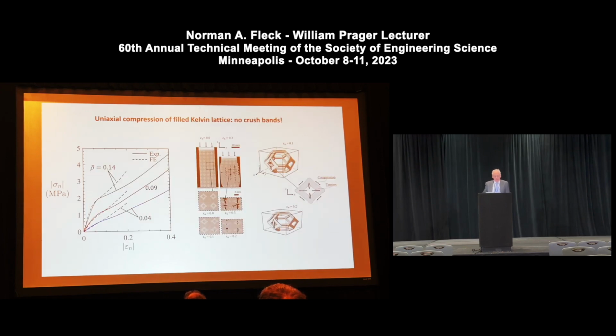And as I've already said, once you fill the lattice, you switch the mode of deformation to a constant volume mode, and the stress strain curve, here's the case of 9% as before, has a strongly hardening response. The dashed line is the calculation which shows that behavior. Interestingly, the finite element simulation is somewhat stiffer and stronger past the initial peak, initial yield value, and that's because the simulation did not include the formation of cracks, tears, which one observes. First of all, the mechanism seems to be that at these junctions between the rubber and the struts, the deformation mode involves transverse stretching of the rubber, and so the rubber tears across, and you get isolated cracks in the rubber, which then grow into the struts and give this observed softening behavior.